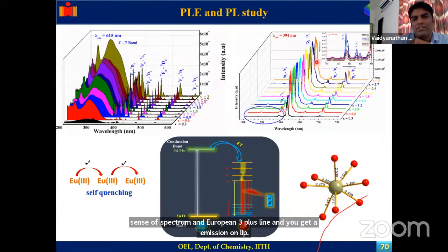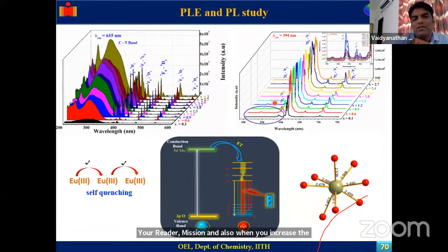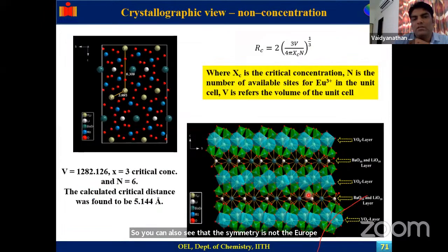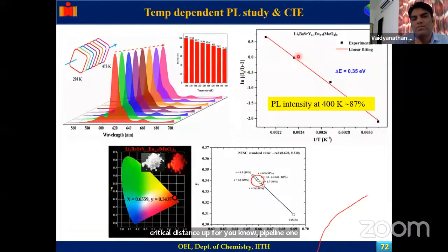Also when you increase the concentration up to 3, you get energy migration. There is no self-quenching. That means when you excite from the valence band to the conduction band, the electron transfers to the europium 3 plus ion. You can also see that the symmetry is not there. The europium 3 plus ion is located in an unsymmetrical environment, and hence you get a red emission. When you come to the concept, you have the layer structure, which has a critical distance of 5.144, and hence we don't get concentration quenching.